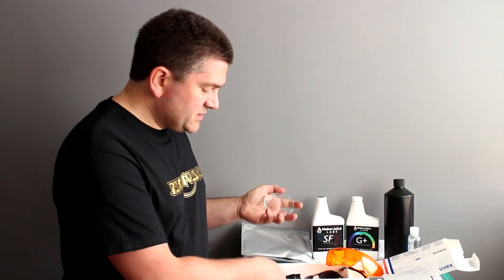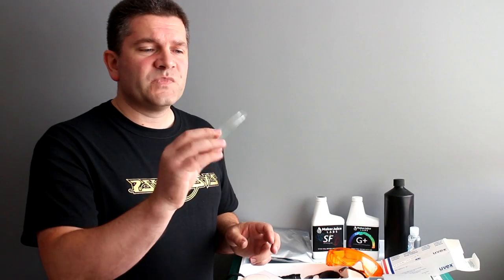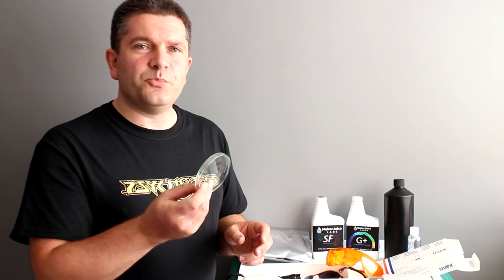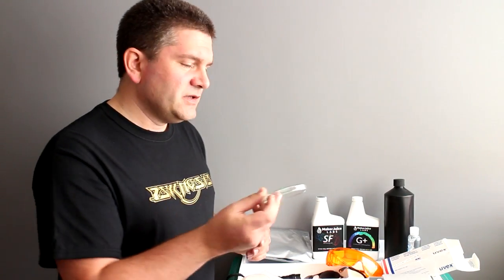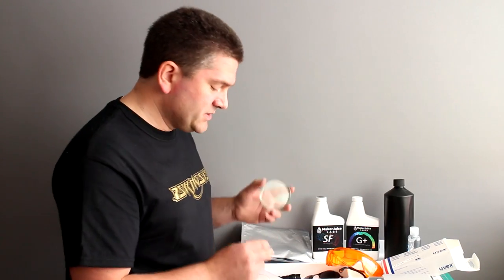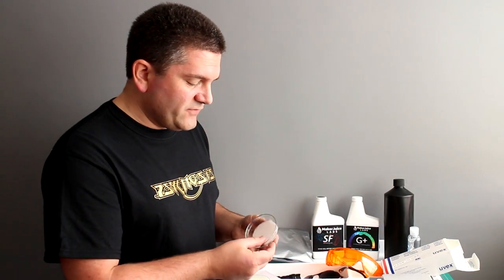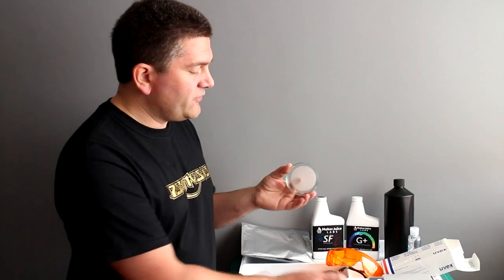Some things obviously let UV light pass through. Obviously glass, a lot of people think that glass blocks UV light. Most glass actually allows UV light to go through, the UV light that we're interested in. The best type of glass is borosilicate which is a very special type of glass often called pyrex but borosilicate glass allows almost all UV light or a decent amount of UV light to go through it.